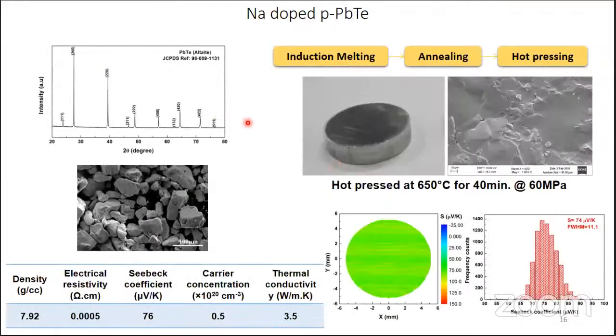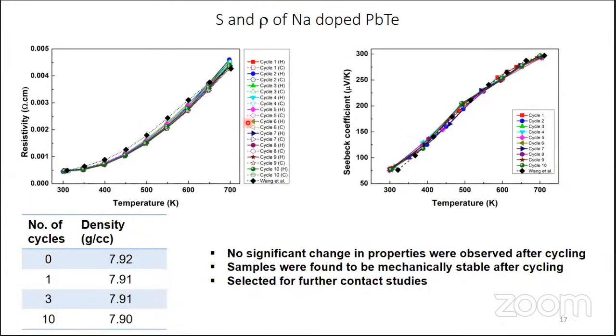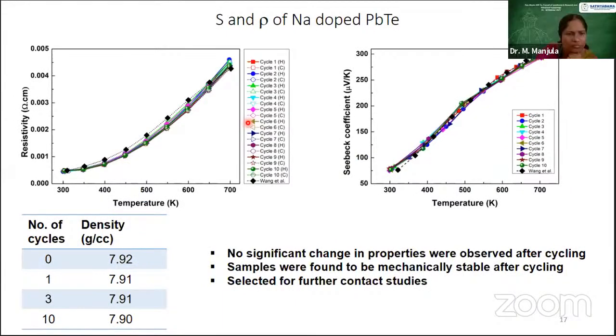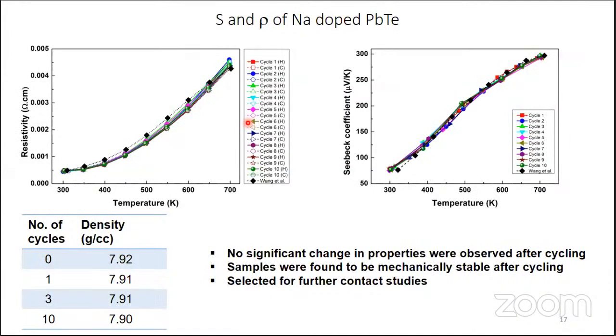This is another lead telluride, sodium doped one. In fact, first we tried this one for our module. We realized that it's not going to work. So then we switched to another lead telluride, which is also a reasonably good performing material. But this material doesn't have such a secondary phase. It's not forming any such tellurium secondary phase.